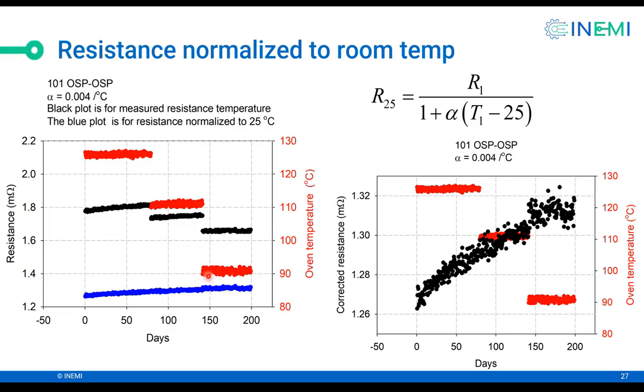In the third portion of the test, we drop the temperature of the oven to 90 degrees, and the resistance drops a little bit. So now there's a jog in the resistance when we change temperature. That's because of the temperature coefficient of resistivity. So when we drop the temperature, the resistance also drops. But we are using resistance as a measure of electromigration, so we need to get rid of the effect of temperature.